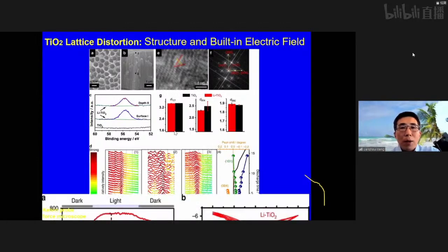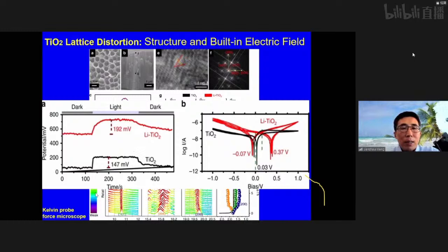We also applied contact potential difference, in relation with the light, to see the difference after we insert the lithium into the system, and we found some built-in electric field in the lithium-inserted TiO2.